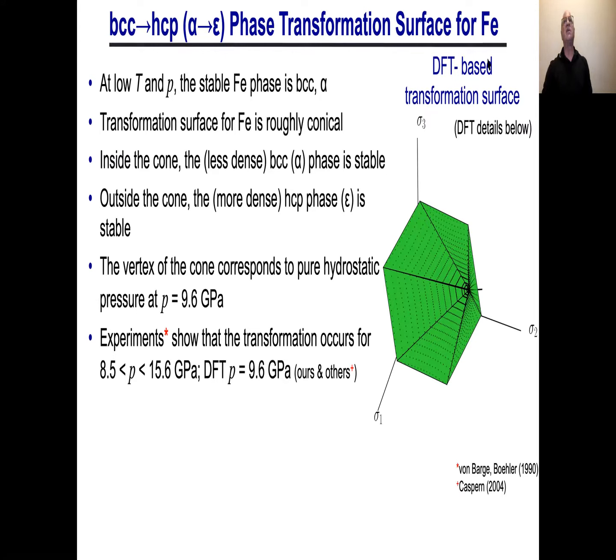But so let's look at iron again, the BCC to HCP transition. So we know that iron is BCC, the alpha phase, at low temperature and pressure. If I look at the transformation surface, which is to say inside this cone, the material is body-centered cubic. That is, if I go all the way down to the origin at 0 stress, it's body-centered cubic. And outside the cone, it's the more dense phase, which happens to be the epsilon or close-packed HCP phase. Okay. The vertex of the cone right here is right on the pressure axis, and that point is along that axis at 9.6 GPa. But experiments show that the value can actually be between 8.5 and 15.6. And we'll come back and talk about that in a little bit.